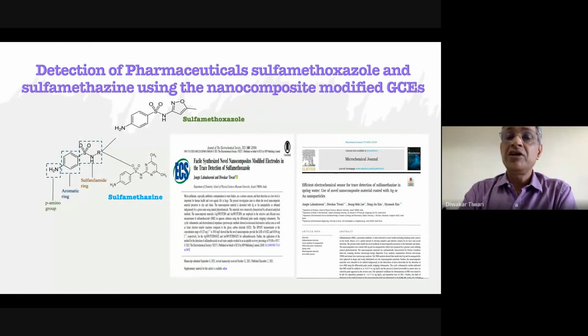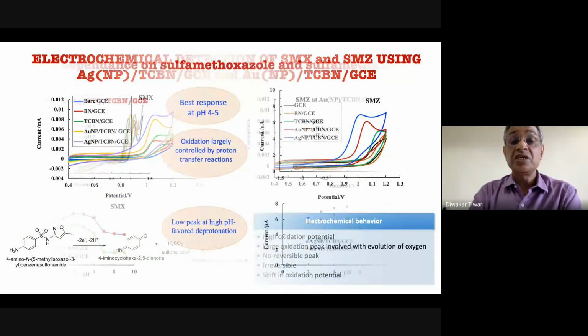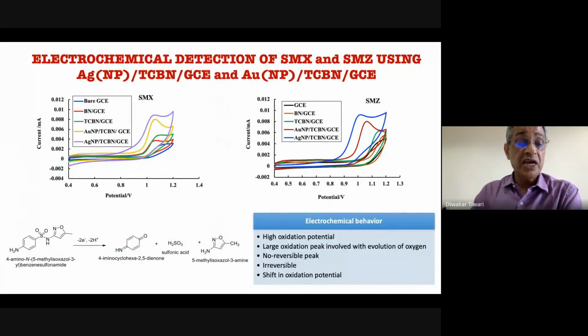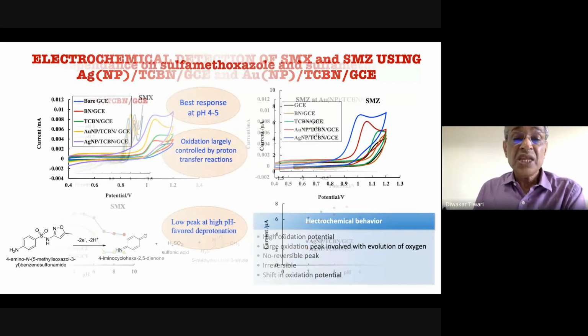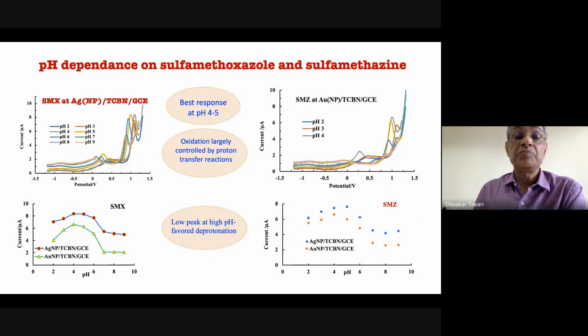And then I'll go very quickly to the pharmaceuticals, the two different pharmaceuticals, especially the antibiotics, sulfamethoxazole and sulfamethazine, which have been published in two different journals, that is ECS, the Electrochemical Society, and the other one is the Microchemical Journal. Already their data has been published. These two materials have been used for the detection of these two. And the cyclic voltammogram shows that this is kind of an irreversible process. Sulfamethoxazole or sulfamethazine is being oxidized but not reduced. That's why a single peak has been observed on the oxidation side. And we have taken the advantage of that, and when we did the pH dependence data, we could see that pH 4 to 5 is an optimum pH for detecting these two pharmaceutical compounds.